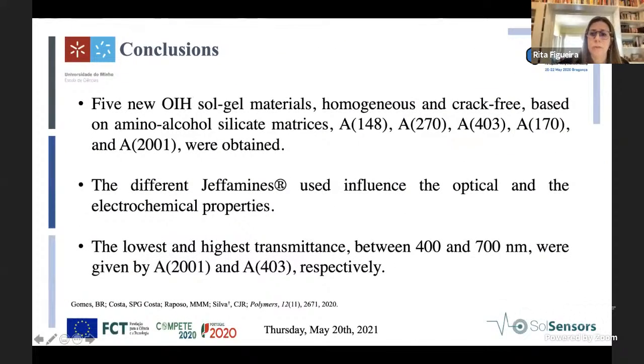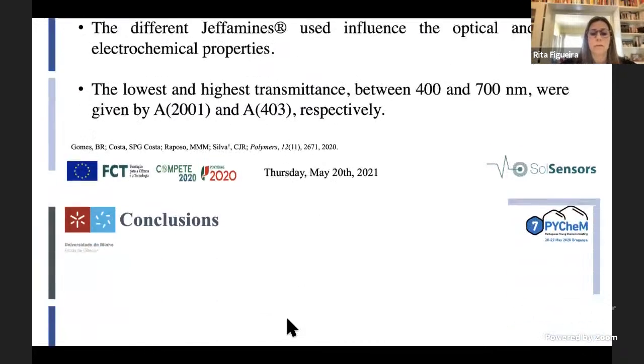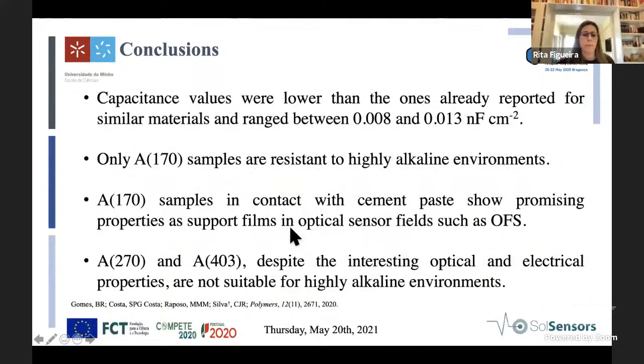In the end, we can conclude that we obtained hybrid sol-gel materials based on amino-alcohol silicate matrices that were crack-free and homogeneous, but the different Jeffamines influenced the optical and electrochemical properties. The lowest and highest transmittance between 400 and 700 nanometers were given by A2001 and A403 respectively. And the capacitance values, which I did not speak about before, were lower than the ones already reported for similar materials.